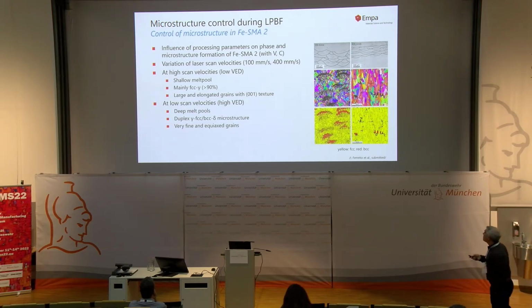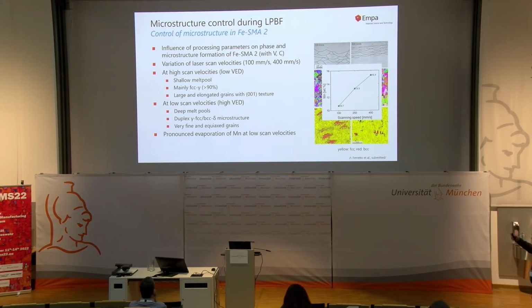Now what's happening here? First of all, we realized that we do have a pronounced evaporation of manganese as a function of the laser parameters. And that's actually something we hoped for. And you don't see error bars. It's because it's so reproducible. So it's not scattering, and this gives us some kind of control to vary the manganese content in our material.